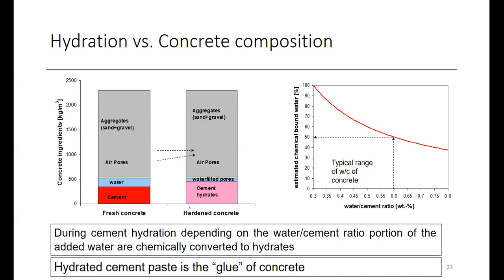And when it becomes hardened concrete, there will be aggregates, porosity, and cement hydrates with a water-filled porous structure. This is the final composition of hardened concrete. And in different aspects, we utilize water-cement ratios. Water-cement ratio means the amount of water that we put in to produce the concrete, a weight or mass-based ratio. Usually in concrete, it lies between about 0.6 and 0.3. This is a typical range.